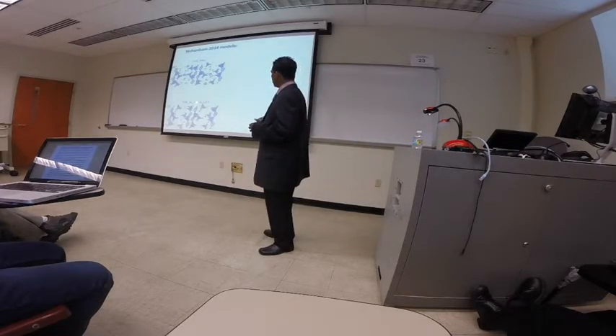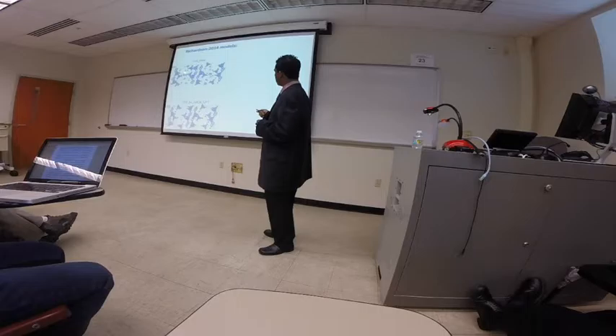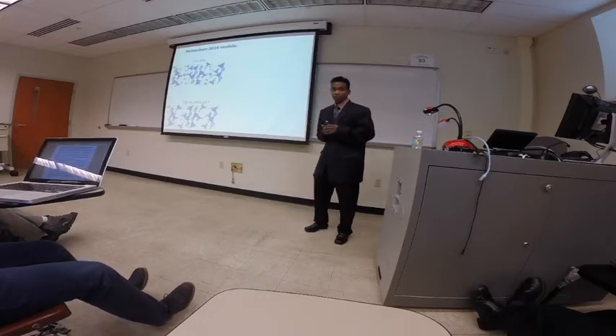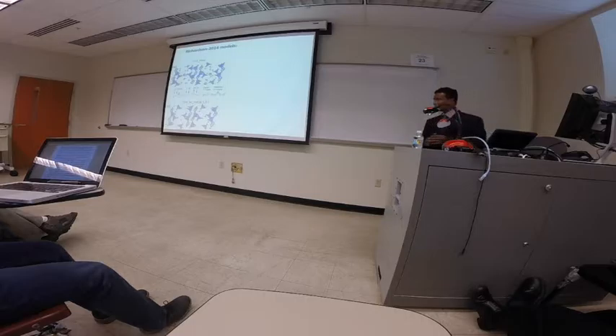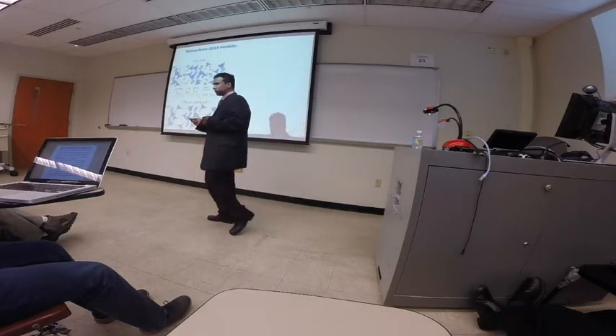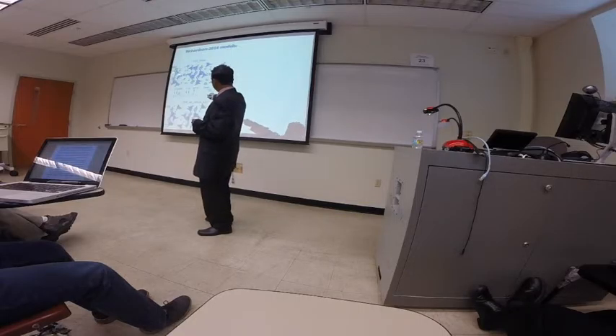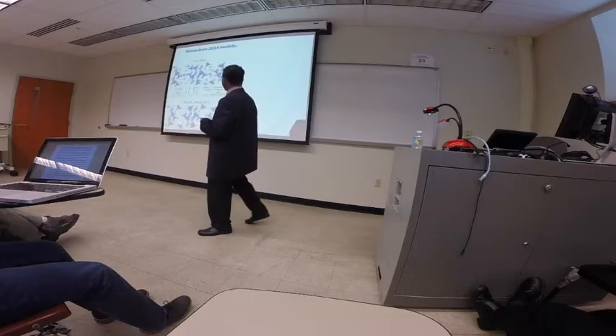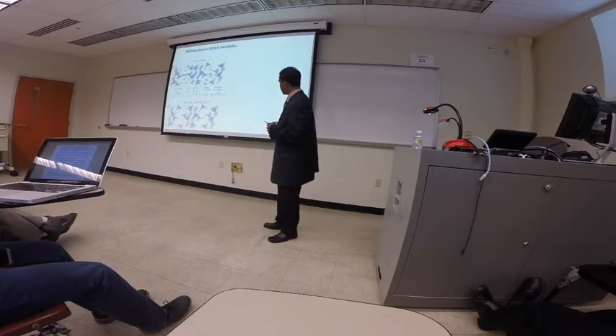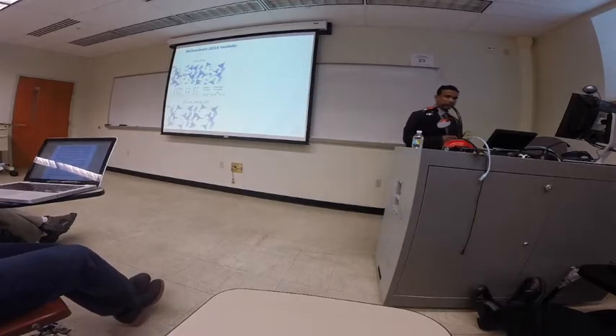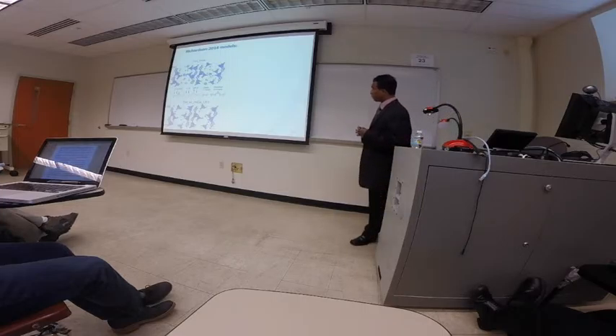So from that 16 crystal database, I took 2 crystals. These are all infinitely long silicate chain crystals. Both of these crystals are layered as a starting point. This study, of course, is still at an early stage. And why I chose these 2 crystals is that one has calcium in the interlayer, the other one has no calcium in the interlayer. And of course, the infinitely long silicate chains had to be taken out because we were thinking to extend this to calcium aluminum silicates. And it is known that the aluminum replacement for silicon can only be done for the bridging tetrahedron. So you have a three silicate tetrahedral chain here, and this is called a bridging tetrahedra in the middle. And aluminum is always replaced for the bridging tetrahedron. And also there's a preferred or maximum percentage of aluminum replacement, which I'm not going to go into detail.